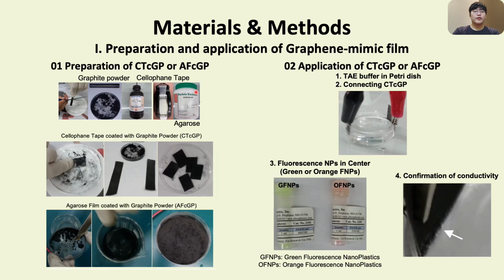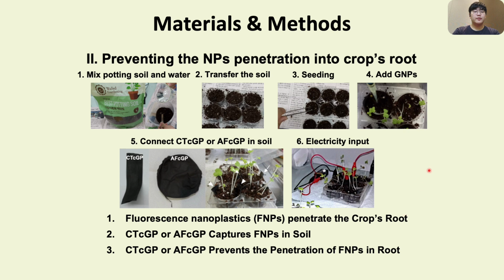I prepared a graphene mimicking film called CTCGP or AFCGP by coating graphene powder onto cellophane tape or agarose. And then I confirmed the film's electrical conductivity by observing bubble formation on its surface when electricity was applied to the film in the solution. Also, I used the film as an electrode to examine the electrical mobility of the fluorescent nanoplastics. Lastly, I tested whether the films with a low voltage could prevent nanoplastics in the soil from penetrating into crops.